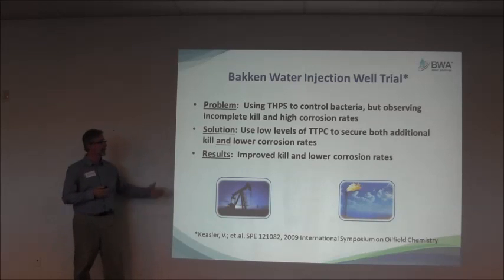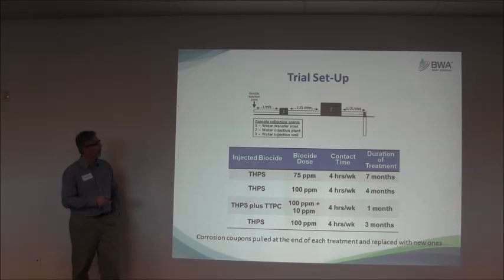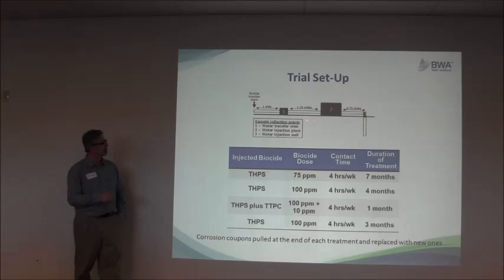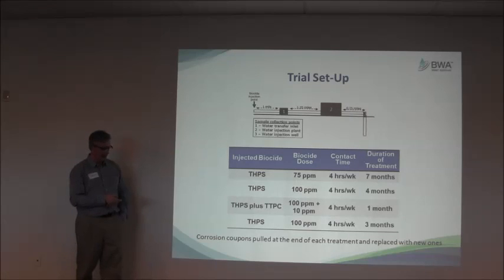In this particular study, they did a joint biocide treatment and got improved results. This was a water injection well system, basically a few miles long — they were adding biocide at the beginning, with a one-mile transfer line to the inlet and an injection plant about a mile down, and the injection well area about three-quarters of a mile further. The study was set up to look at THPS at different dosages and contact times, then a co-biocide treatment, then back to THPS alone.